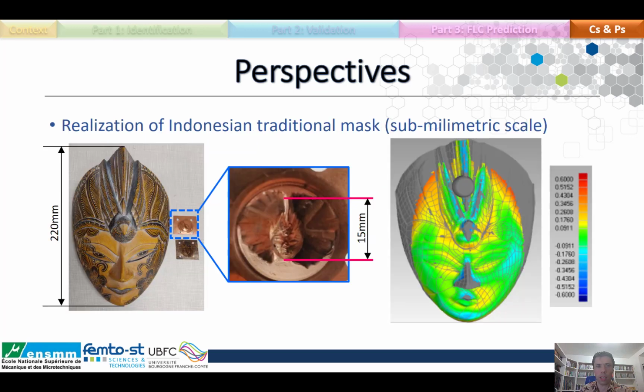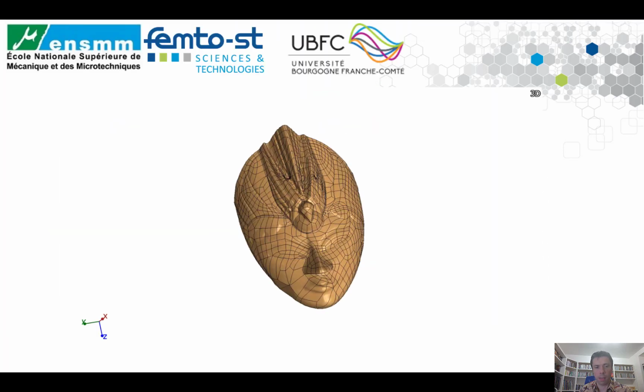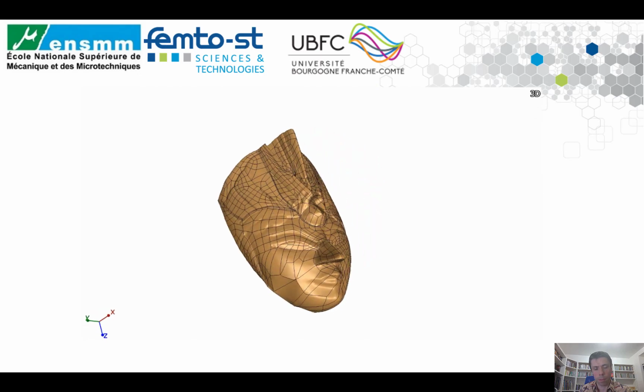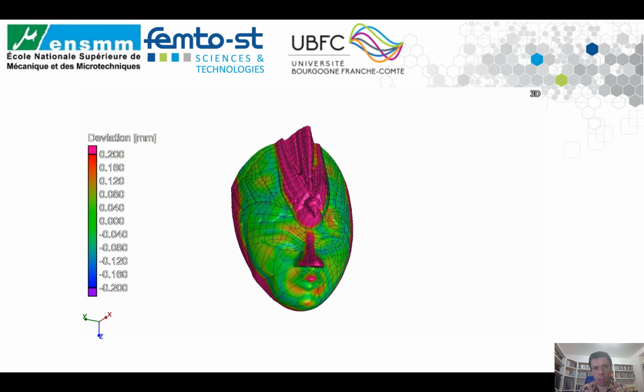We are currently working on the realization of an Indonesian traditional mask at a sub-millimetric scale. So the part is produced with incremental sheet forming, and a simulation of the process is realized by finite element using the material parameters calculated by micro-indentation. This part was measured using a micro-nano tomograph, and the result compared with the finite element result is very good, as we can see in this movie. The difference between both is nearly zero, except for the nose and the bird here in pink, because the tool is too big to produce this thin part when the mask is very small.